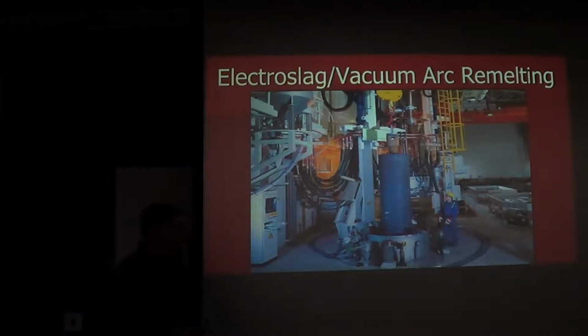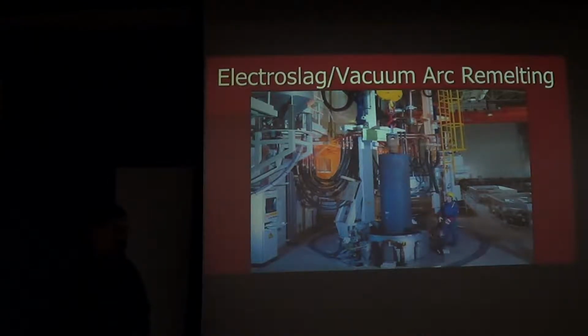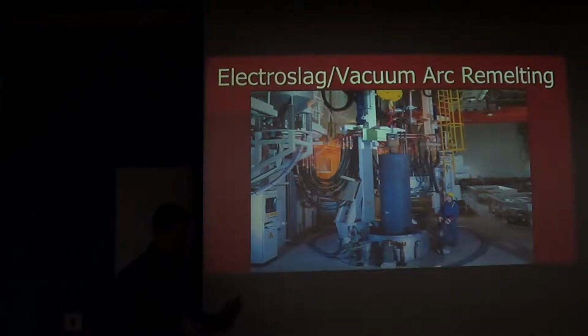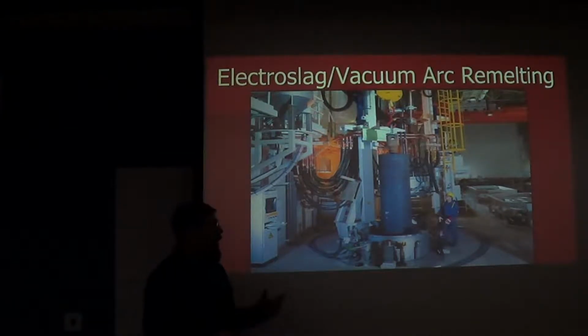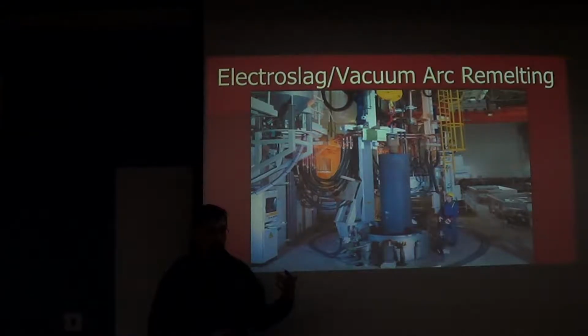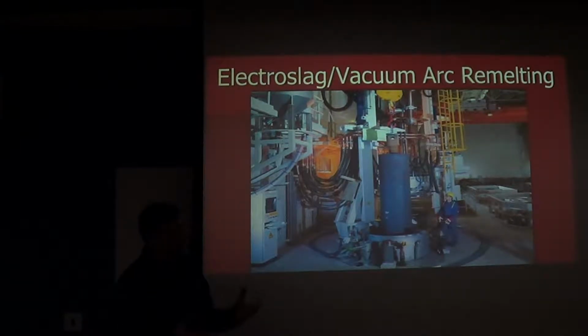So we see in our business that certain stainless grades, say for example, precipitation hardening stainless grades, are quite often remelted using the vacuum arc remelting process, or VAR, and we see other grades, duplex materials, some alloy steels, are made by the electroslag remelting process. So they're all available to us by the single melt process or air melt process, but then the remelt process is kind of tailored to different grades based on what you need.